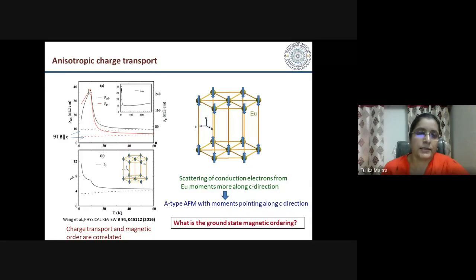So exactly at the magnetic transition, we also see a peak in the resistivity, and then the ratio of rho AB upon rho C, the anisotropy, actually rises below this transition temperature. So along the C direction, it seems that there is more scattering than in the AB plane. Based on that, it was proposed that this could have an A-type antiferromagnetic structure with moments pointing along the C direction. But it was not known exactly what the ground state magnetic order is here.